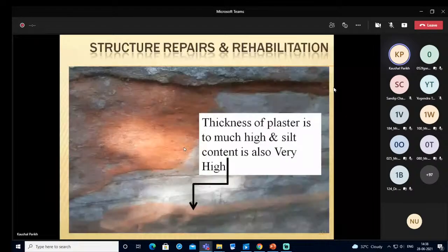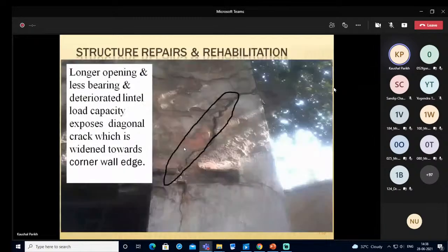This is one of the typical things that can be visualized in older structures because of the higher silt contained in the plastering work. Inclined cracks can also be visualized because of the longer opening and less bearing, due to the lintel's load carrying capacity, which exposes diagonal cracks and requires a specific rehabilitation technique.